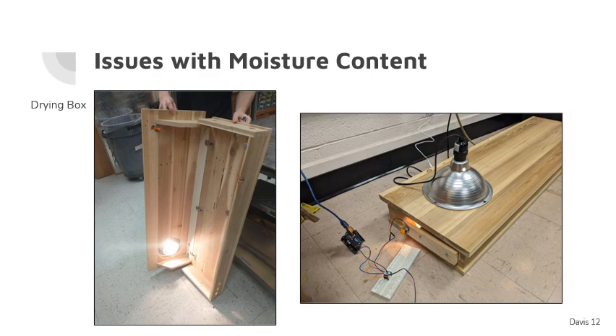So this proved to assist somewhat in our drying process as well, where any fronds we put in there for several days came out significantly more dry than any that were just sitting on the outside. So that was good to see, and we hope that this box is utilized further in future capstones, as well as a rack was ordered and assembled that we were able to put palm fronds on outside of the box to allow them to dry as well.